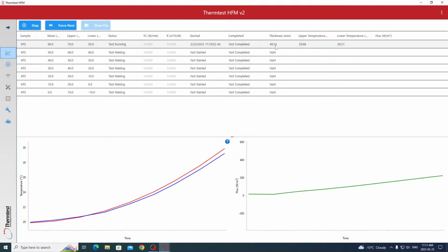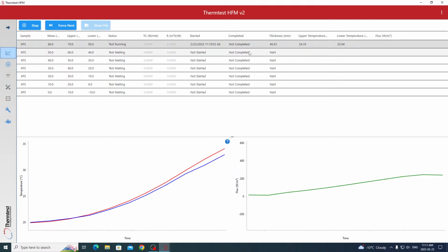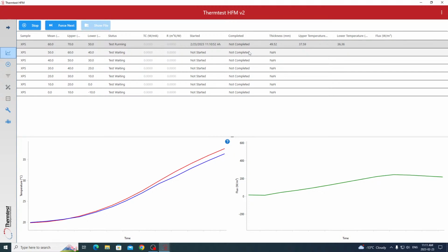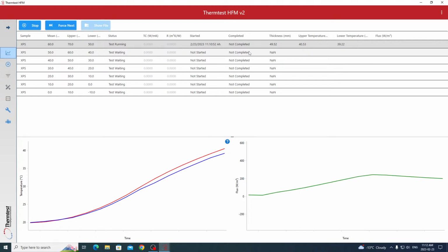You can see the thickness was measured at 49.52 millimeters. You can see the current temperatures. But what I can do, so we're certainly not going to watch this run, because each measurement of a 2-inch XPS would take 45 minutes or something like that, just due to the high resistance. Average test time of a 1-inch would be 30 minutes approximately. But what I can do is open up the software in another application and show you what this measurement set would look like, which I have here.